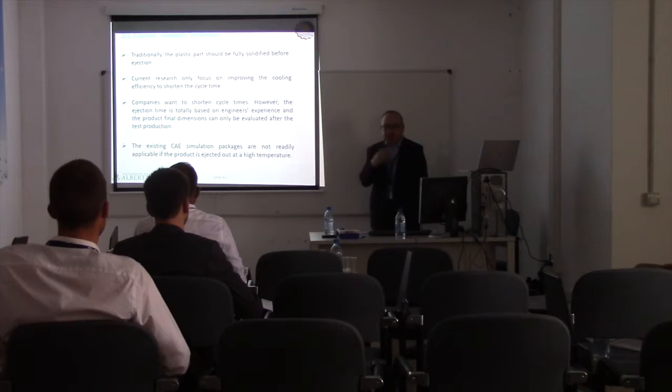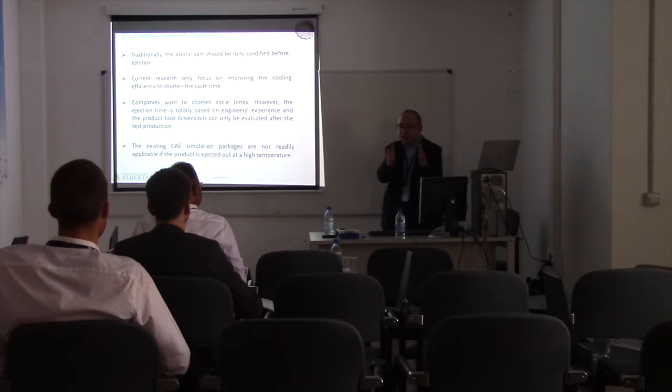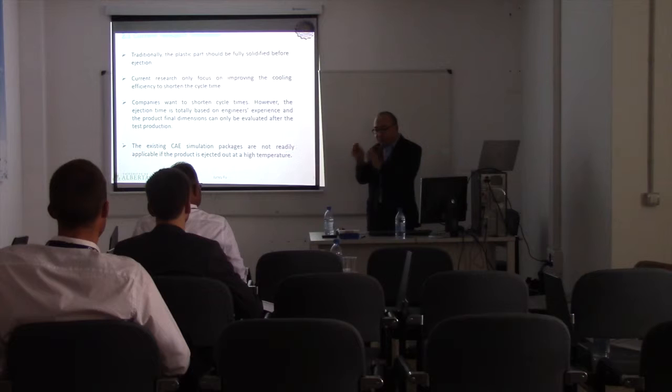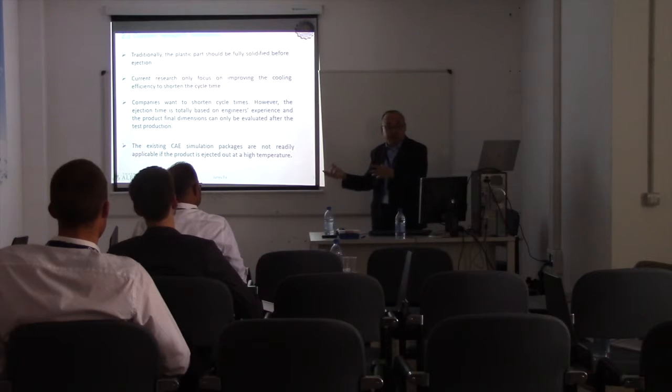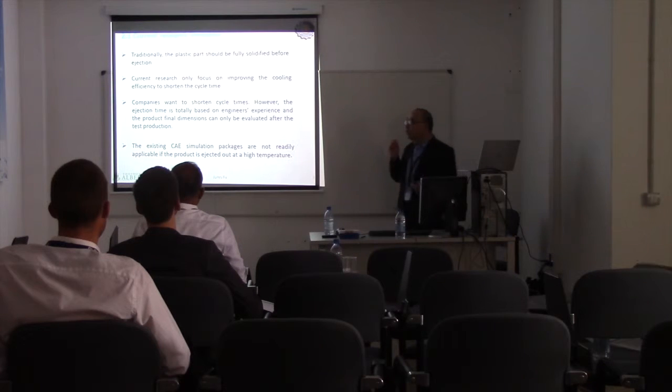And then usually the company sets up their process using a conservative approach, basically making sure you have long enough time to cool off. And then we start to think: if you really want to improve the process and compress the cycle, I can semi-finish and eject, but I know that the material is still hot and the inner side is still liquid or semi-liquid, and then you put it into the air, let the air cooling happen, and then you can save the cycle time. And we have to predict that with finite element analysis.